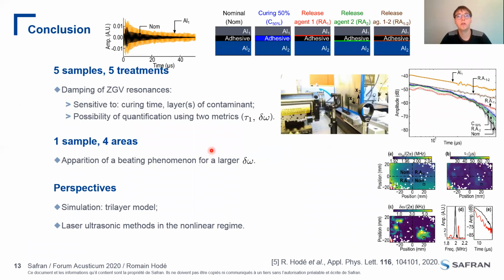So to conclude, we have manufactured 5 different samples with 5 different treatments, and we have studied the damping of ZGV resonances. And we can see that this attenuation is sensitive to curing time and layers of contaminants. And we have a possibility of quantification using the 2 metrics, τ1 and delta omega. And when we have 1 sample and 4 different areas, we can see that we have an apparition of a beating phenomenon for larger delta omega due to the frequency around 1.9 megahertz.